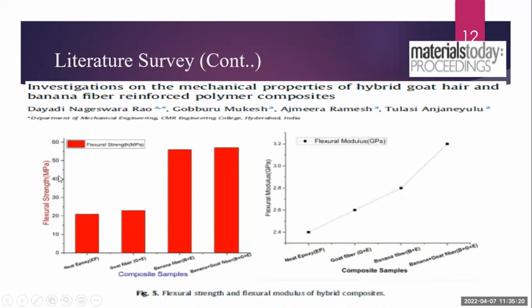After the flexural test, they found that the flexural results were also very good. Although the banana fiber shows good results with the epoxy, if banana fiber is mixed with goat fibers and fabricated with the help of epoxy, the flexural strength increases slightly. But here we can see we are getting some differences between these two. And the flexural modulus is clearly very much higher compared to pure banana fibers and epoxy.